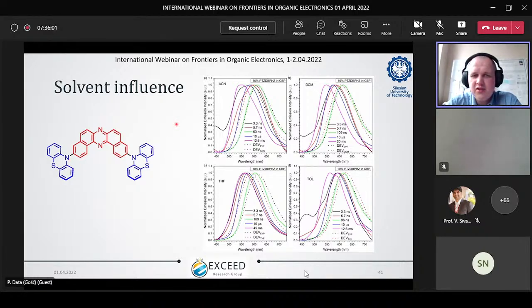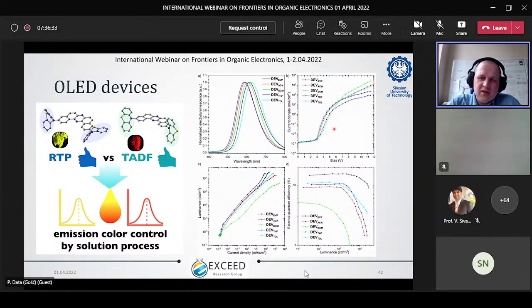As I said previously, we can also manage our conformations in the solid state using different solvents for the deposition, for the spin coating. So I spin coat different devices using different polarity solvents, and then compare to our pure crystal conformer emission, and check how they behave and if that's the equatorial or axial conformer. If you want to, it's really nicely presented in the paper, but generally it affects our conformations, and you see that it's actually the other way around from what it was in the solution photophysics.